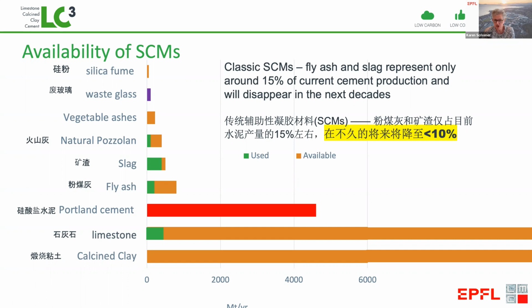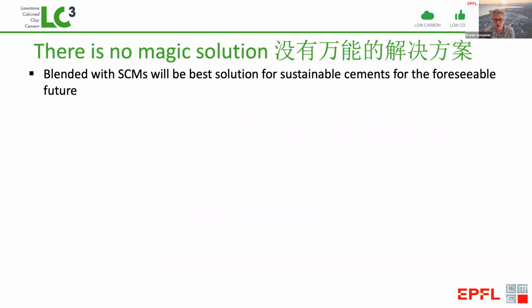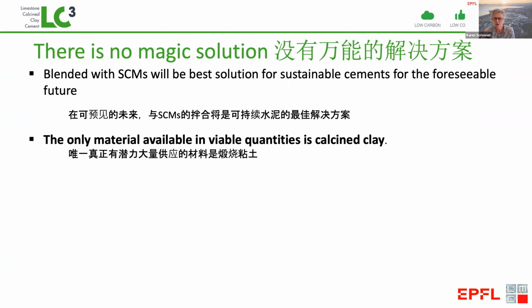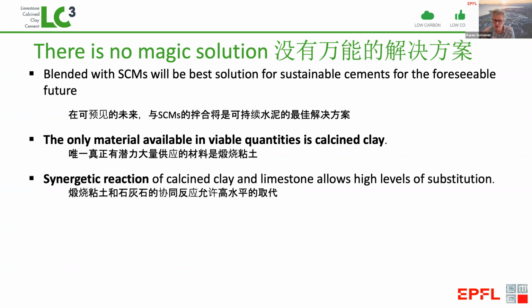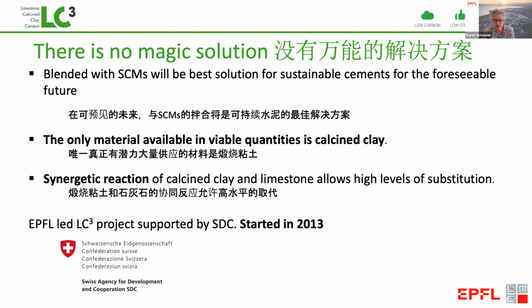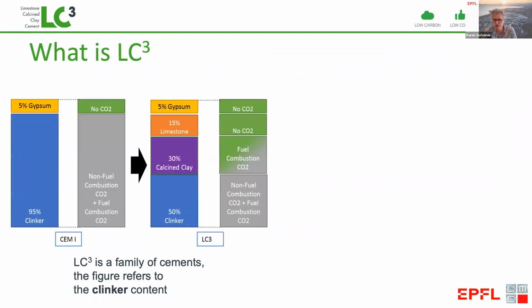What can be a real game changer here is our clays, which when they're calcined, that's to say heated to about 800 degrees, produce very reactive materials. So this is behind our invention of LC3, to realize that SCMs are the best solution for the sustainable future, that the only material we have in viable quantities is calcined clay. And this is the really new novelty, that we realize that there's this synergetic reaction between calcined clay and limestone that allows very high levels of substitution. So this was a project we christened LC3 and has been a project supported by the Swiss government since 2013.